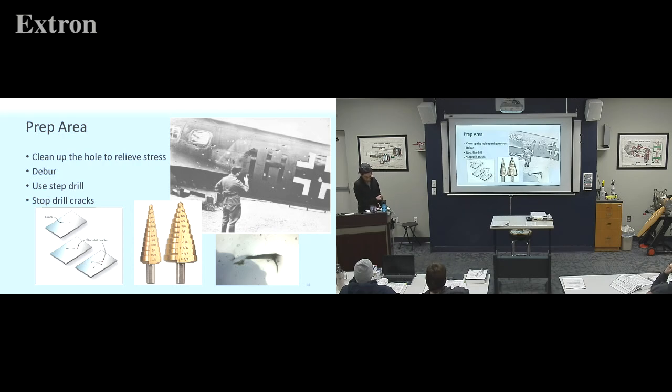AC 43.13 on page 4-40 gives a general rule of thumb. And 4-40, top left-hand side says drill small holes, 3/32 inch or 1/8 inch, at the extreme ends of the cracks to minimize the possibility of their spreading further.